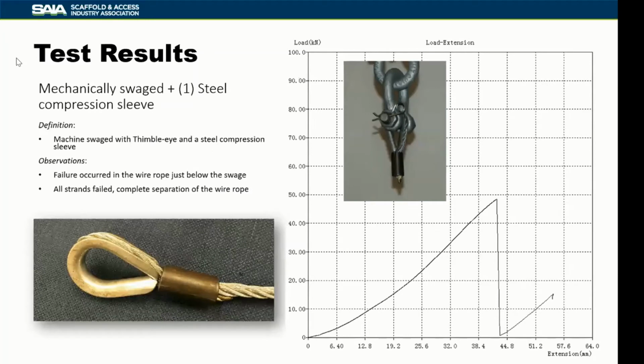Looking at mechanically swaged type fasteners still, but looking at a steel compression sleeve rather than copper or aluminum, you can see again in the inset picture where the failure occurred, which was in the wire rope, again just below the swage. On this one, all strands failed. It was a complete separation of the wire rope from the termination. Breaking force was a little bit less than what we had seen in the previous mechanically swaged terminations, and the extension or elongation was roughly the same, right between what we saw with the copper and with the aluminum.